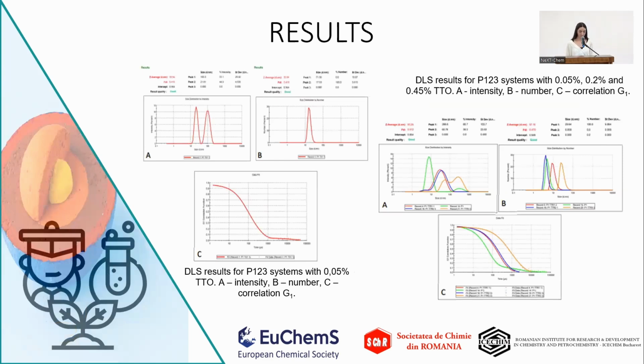The DLS results for the P123 system with the lowest concentration of tea tree oil show the existence of two peaks in the intensity mode of the diagram. This implies the existence of two different sizes, two different populations of aggregates. But in reality, the majority of the aggregates are actually only one size, approximately 20 nanometers. Also, this is confirmed by the correlation function right here, which shows the existence of a bimodal dispersion, meaning two populations. But again, in reality, there is only one.